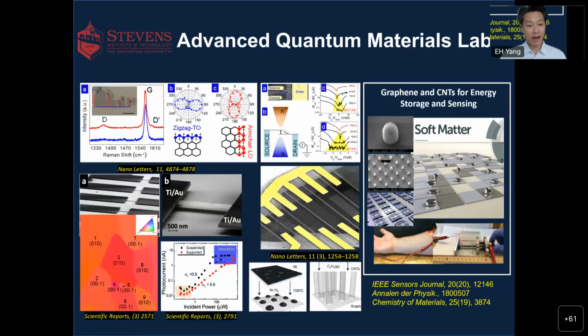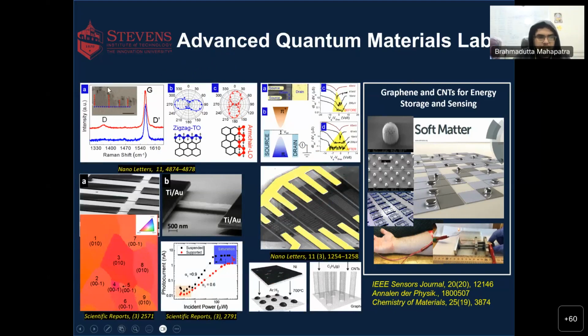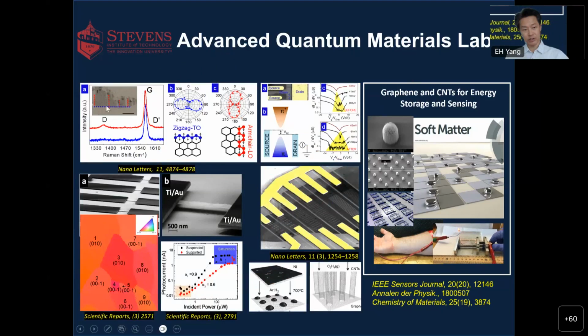Regarding the graphene, we worked on optically purifying the edges of these graphene structures. Do you see this cursor? Do you see this arrow? Sir, it's visible. Okay, good. Thank you. So here we have the armchair and zigzag directions of this graphene flake. This is exfoliated graphene, done a long time ago. You use polarized light to selectively burn zigzag edges, leaving the armchair edges. When you have these armchair edges in a graphene nanoribbon, they are supposed to have an increased bandgap, which we showed, as shown here.